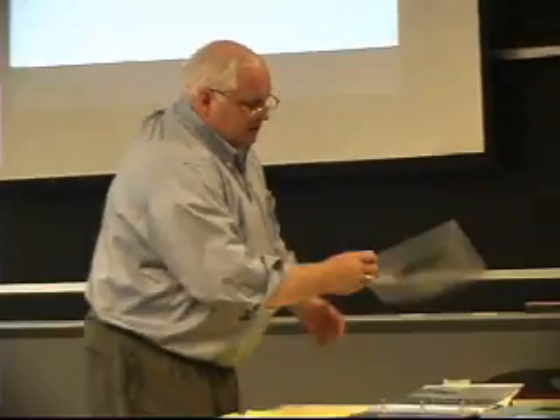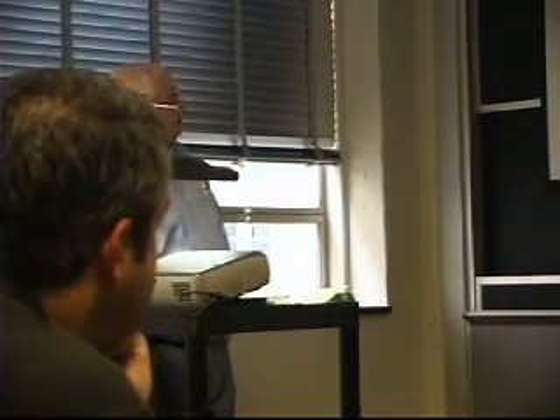This next thing is actually a figure out of the structural welding code, and this was developed by Bruce Graville. It basically says, here's your carbon content, and I said a 0.4 carbon steel is fairly high carbon. 1008 is down here, very weldable. Here's your carbon equivalent, here's your carbon, so you're plotting the two, and anything below 0.1% carbon is very weldable. It's almost impossible to cause hydrogen cracking.